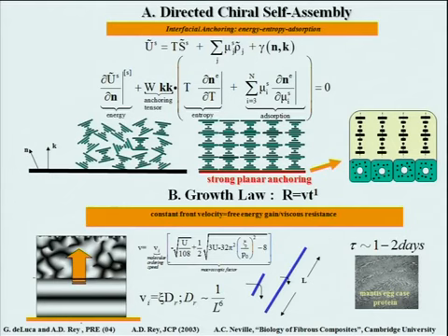The other point is the growth law. So here we have phase ordering. R is proportional to Vt to the first power. So V is a constant velocity, there is no mass transfer. More complicated systems might couple, so might have order parameters, conserved, non-conserved. In this Q-tensor model, we have a non-conserved order parameter, so the velocity is a constant.